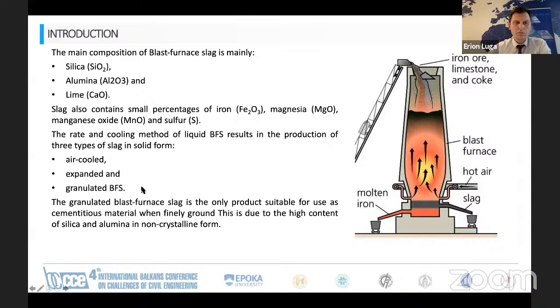And the third one is the granulated blast furnace slag, which is produced by the fast cooling of the blast furnace slag. In this case, as the cooling process is faster, the slag will not have time to form a crystalline structure, but we will have an amorphous structure of the slag. And this type of slag, when finely ground into a powder form, can be used as an additional material or as an admixture to the cement during the production of cement or in the production of concrete, etc. But for sure, it should have certain qualities, some of which we have tried to investigate in this research.